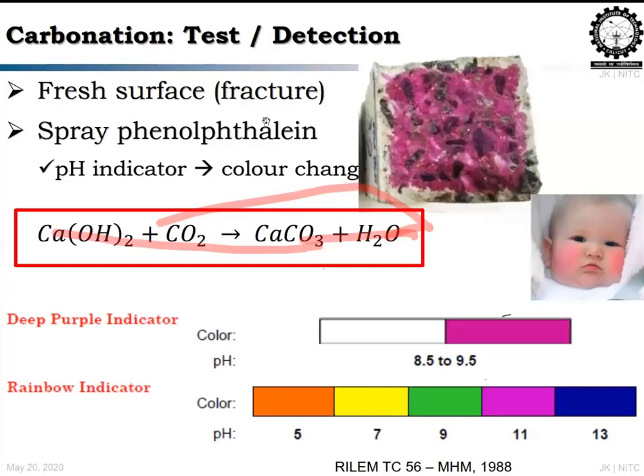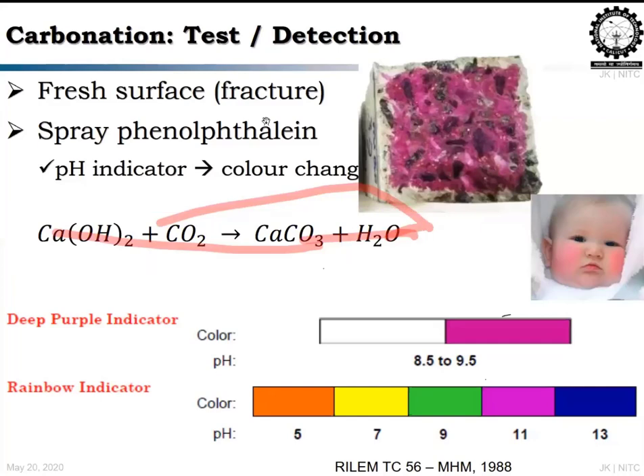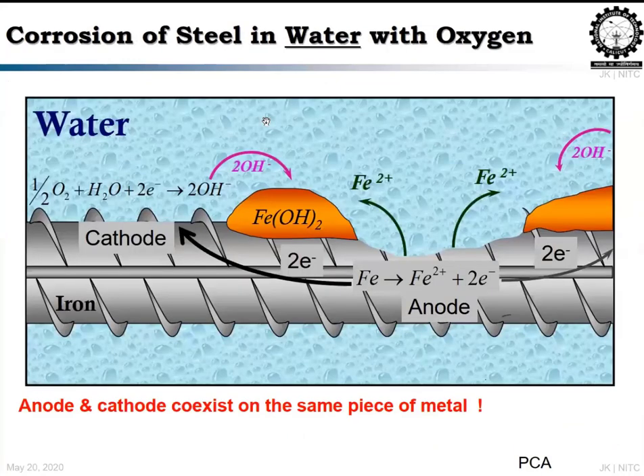So because of that, the CSH structure will collapse, and it will allow all other aggressive parameters to move. This is one serious issue. And if you are looking into corrosion of steel, there are different mechanisms. One is rusting, which is because of the presence of oxygen and moisture, and the other one is chloride. With the presence of oxygen and moisture, corrosion takes place, as we see everywhere.